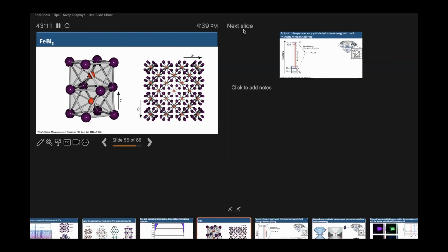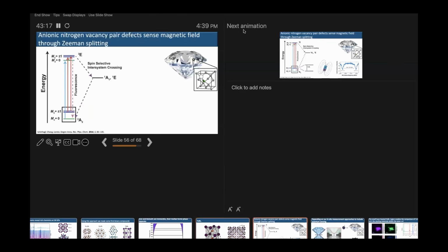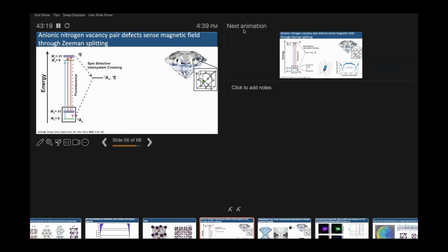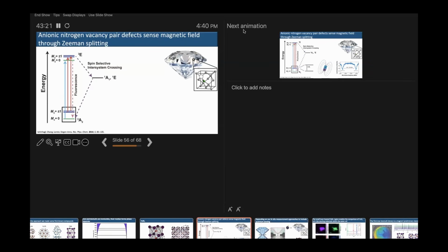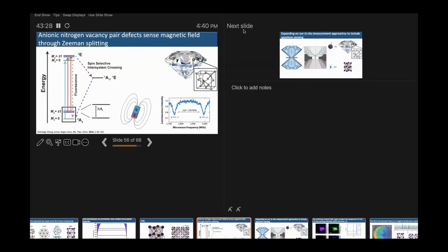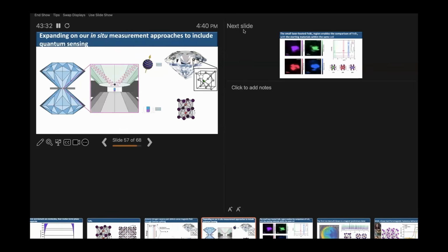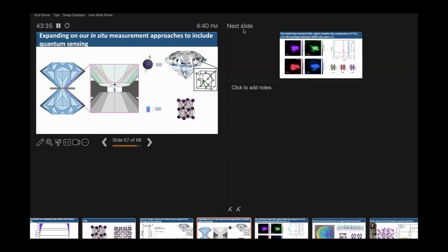And so I'm sure the answer is obvious to you based on the first part of my talk and all of your extensive physics knowledge. There is a thing in a diamond, which is called an anionic nitrogen vacancy pair defect, which can be used to sense magnetic fields. And so we've been collaborating with Norm Yao, because this is really hard, too hard for me. Norm's great. To measure the magnetic moment of iron bismuth trapped within a diamond anvil cell.